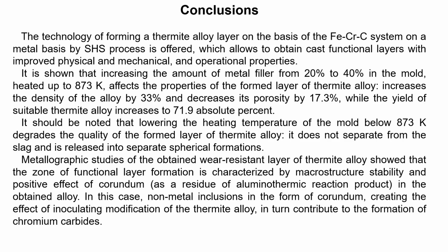So, the technology of forming a thermite alloy layer on the basis of the ferrum-chromium-carbon system on the metal base by self-propagating high-temperature synthesis is offered, which allows obtaining a cast functional layer with improved physical, mechanical and operational properties. It is shown that increasing the amount of metal filler from 20 to 40% in the mold heated up to 873 kelvins affects the properties of the formed layer of thermite alloy, increases the density of the alloy by 33% and decreases its porosity by 17%, while the yield of suitable thermite alloy increases to 71.9 absolute percent.